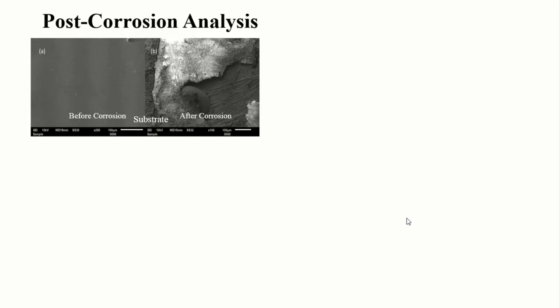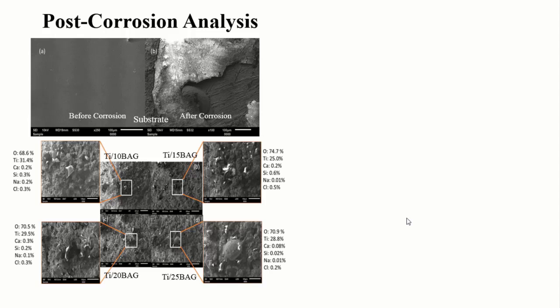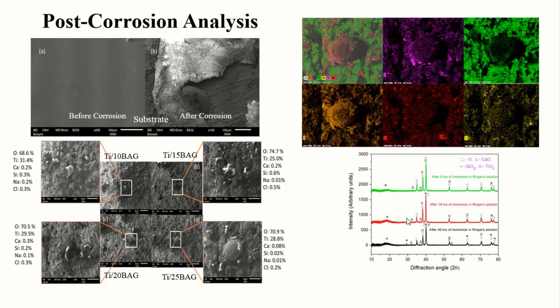Post-corrosion analysis has also been performed, and the SEM micrographs after the corrosion revealed that the top surface of the substrate has peeled off after 2 hours of immersion. However, if you see, in the case of coatings, because of the formation of an oxide layer over the surface, corrosion resistance has improved. The formation of these oxide products has been confirmed by performing XRD analysis on the corroded coating samples.